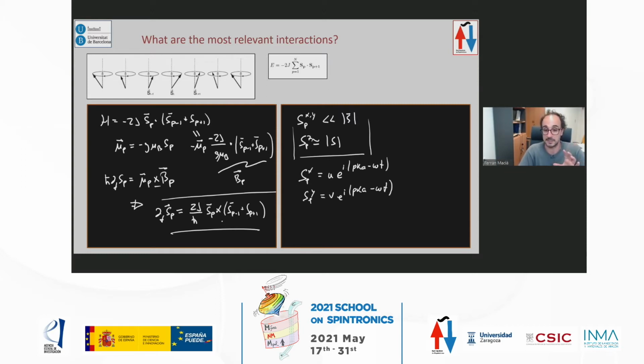So this is a very simple exercise, but to me it's very important, because the thing we're going to find is that h bar omega is, let's see if I'm not wrong, should be 4JS times 1 minus cosine of ka. And you know that for small values of this wave vector, the cosine of x is approximately 1 minus x squared, well, x is ka. So this can be approximated by 2JS (ka) squared.